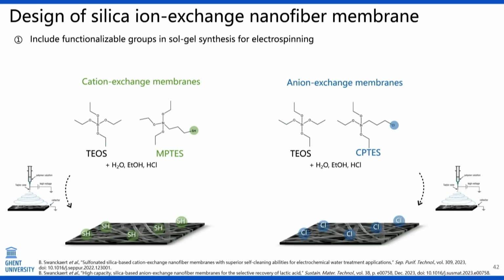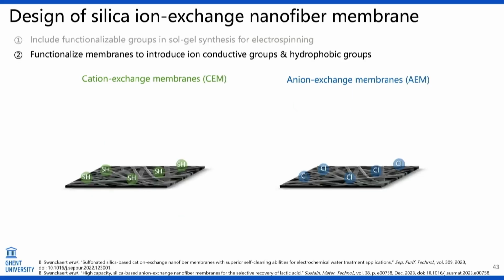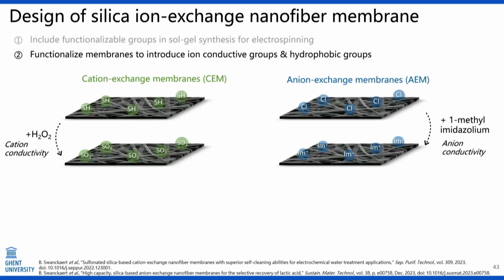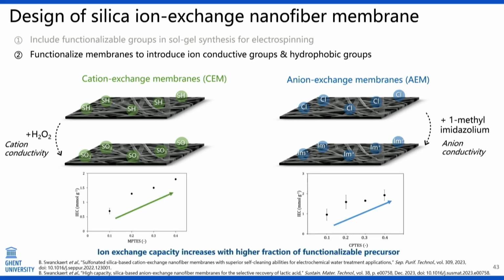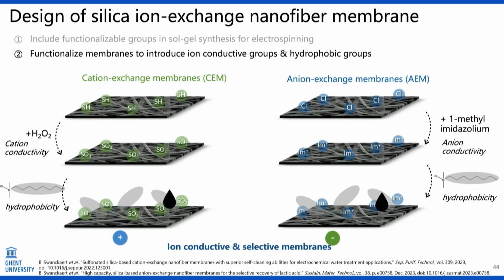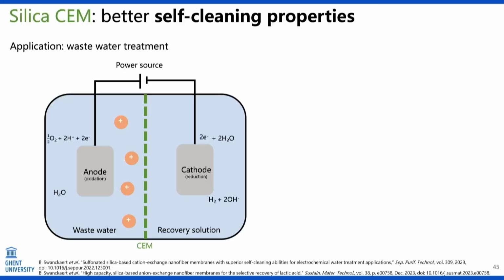We then spun them into membranes, and the functional groups are present, and these functional groups can then further be tuned, in this case, towards a conductivity: for the cation exchange membranes a high cation conductivity, for the anion, of course, a high anion conductivity. And of course, the conductivity was increased depending on the ratio of functionalizable precursor. We also needed the membranes to be hydrophobic for these applications, so we functionalized them with a hydrophobic precursor. And then we can use them as ion exchange membranes, for resource recovery of, for instance, wastewater.